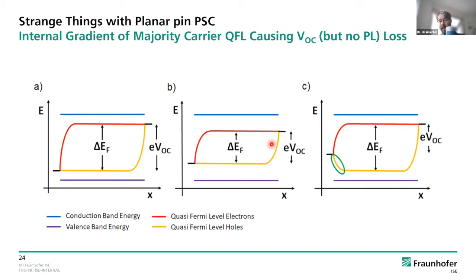What will happen? Again, after some time, I reach a steady state condition because I'm still pouring the same amount of water, which symbolizes the generation of charge carriers. But now, due to the second hole, the filling level will decrease and the new equilibrium will be reached. So again, per time unit, what is going in is going out, but now I have 2 holes, so the filling level will be lower. This is exactly what you can see here in the middle. You have an additional loss mechanism. It leads to a decrease of charge pair concentration, and therefore quasi-Fermi level separation, and you will measure a lower open circuit voltage. But still, the PL intensity, which is then also lower, will still be correlated to the open circuit voltage.